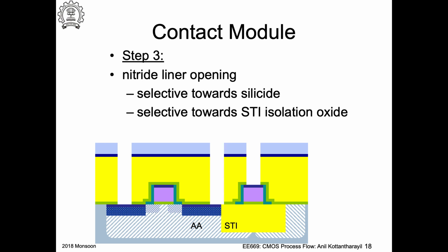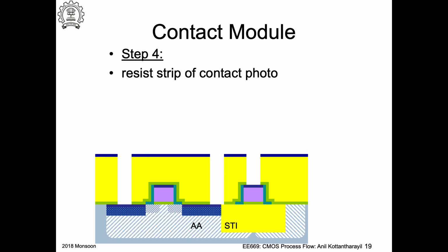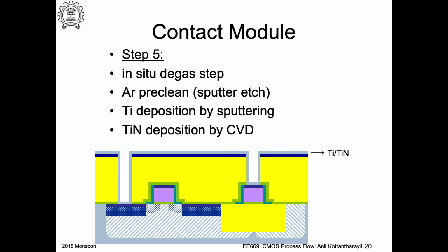Okay. So this etch should be selective to silicide, and some regions it may also actually hit the STI, so it should be also selective to STI also. And you remove the photoresist, that's fine. And then you want to put some metal on top, right? So typically you want to remove any dielectric residues on top of the exposed source drain and the gate regions, right? Polysilicon top contact regions.